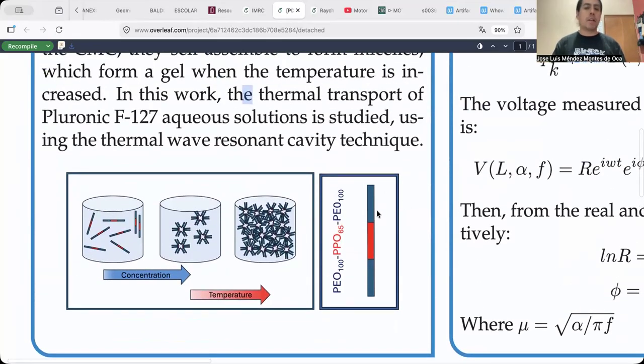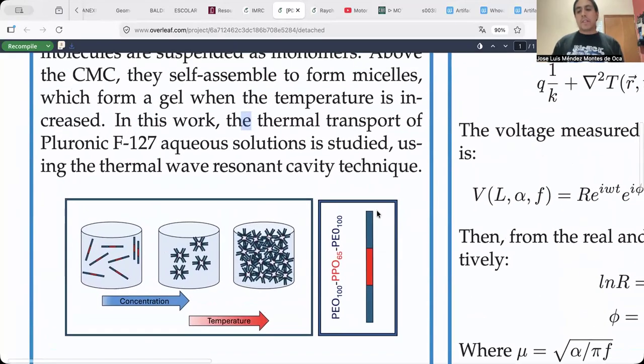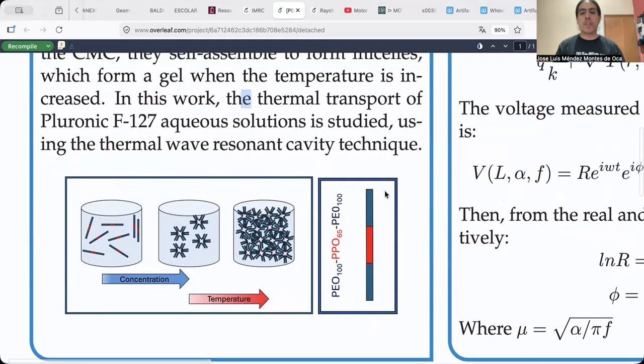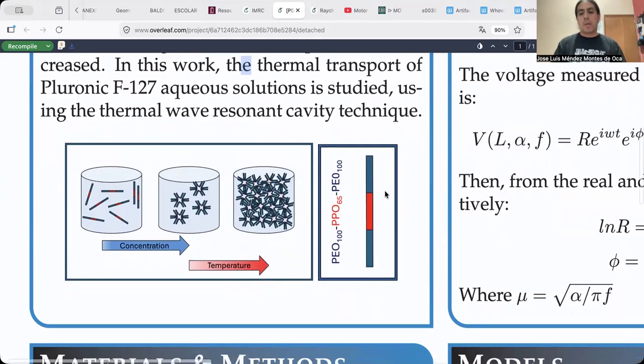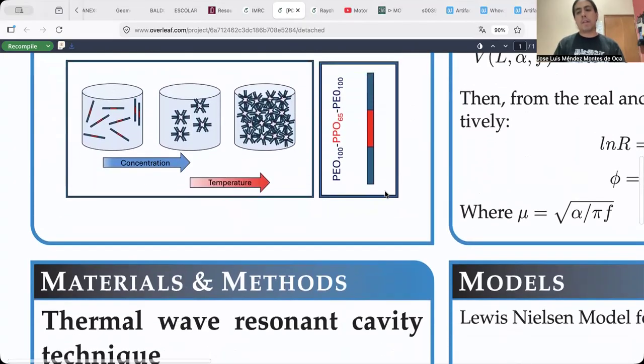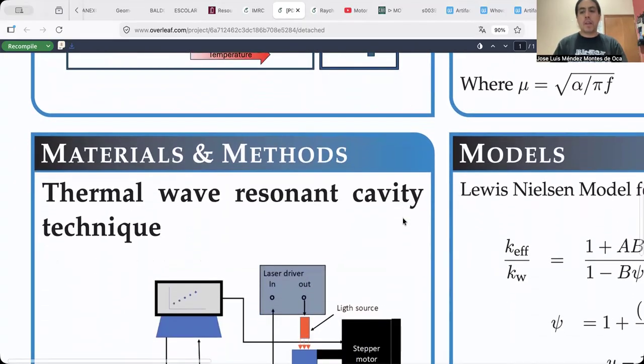This is the molecular structure of the pluronic. And well, this transition usually is observed by changes in the density or in the viscosity of the solutions. But from a thermal point of view, it is difficult to observe. Calorimetry can be used, but the heat capacity changes when the formation of micelles occurs, but it remains almost constant during the gelling process. So in this work, we observed these transitions using the thermal wave resonant cavity technique, which enables us to obtain the thermal diffusivity of the samples.